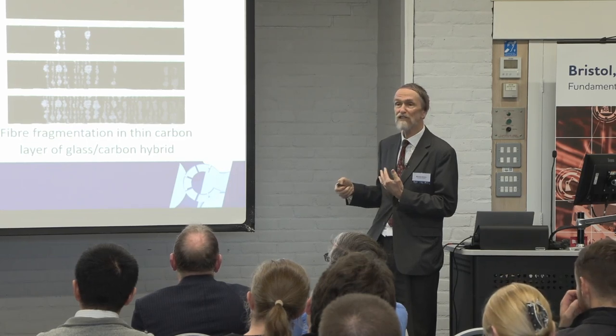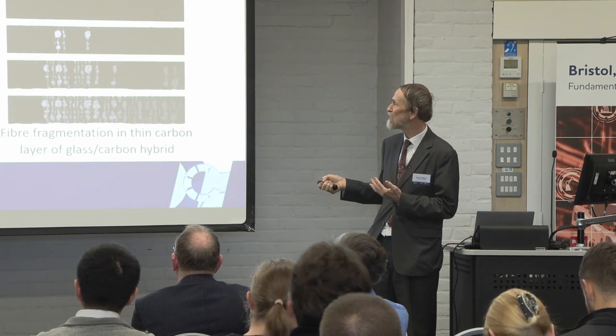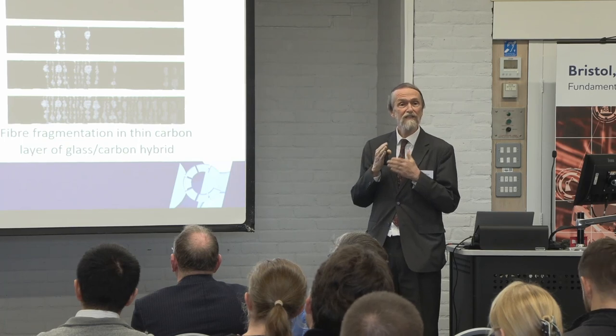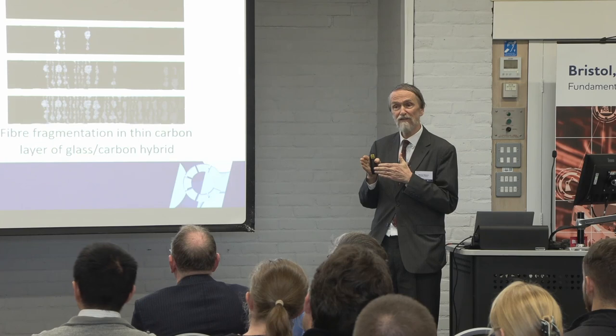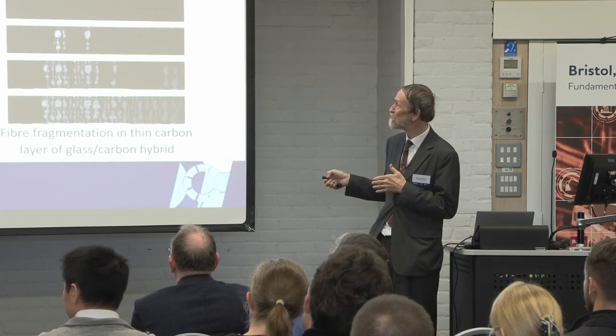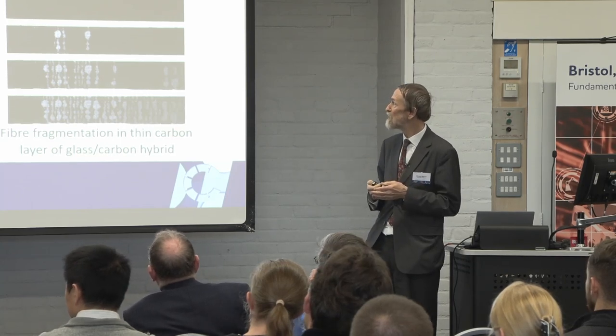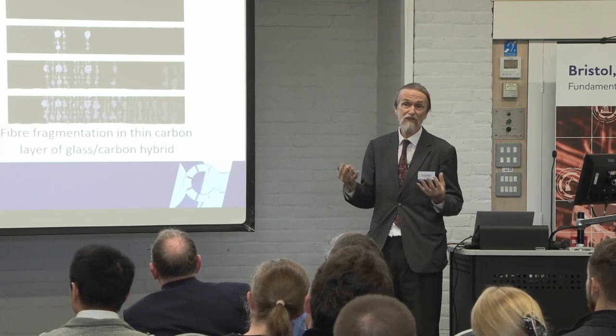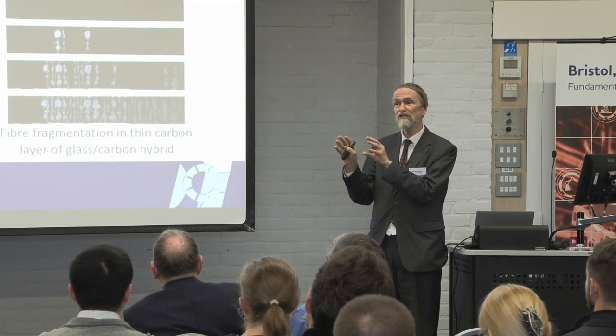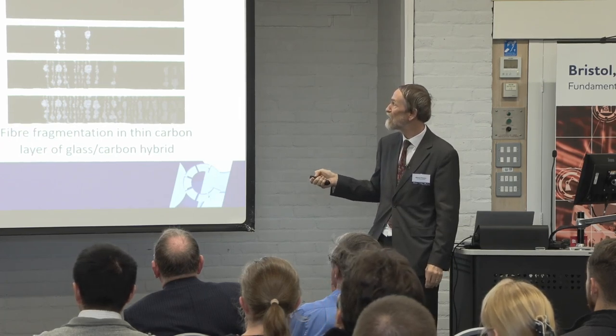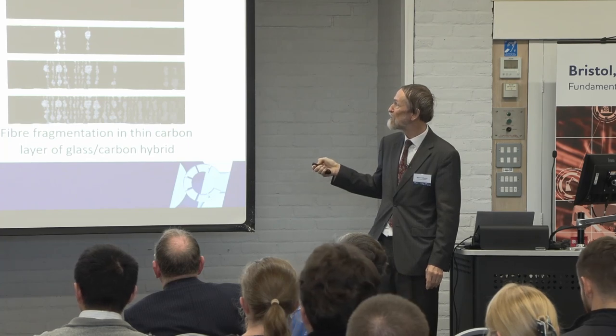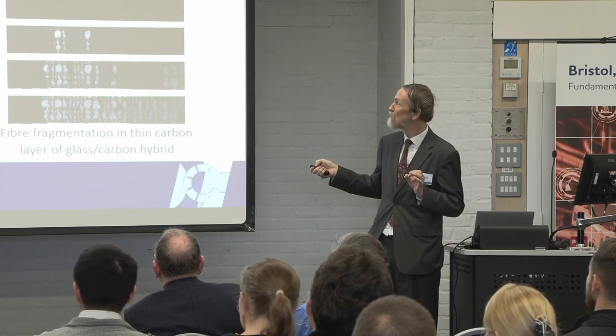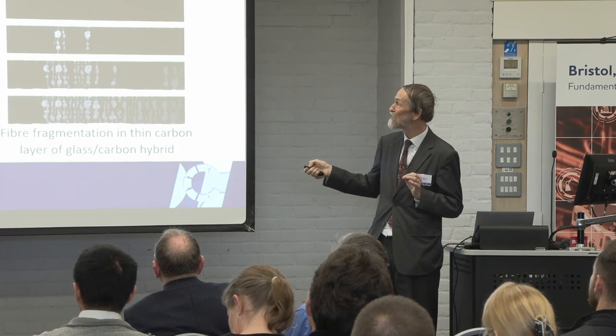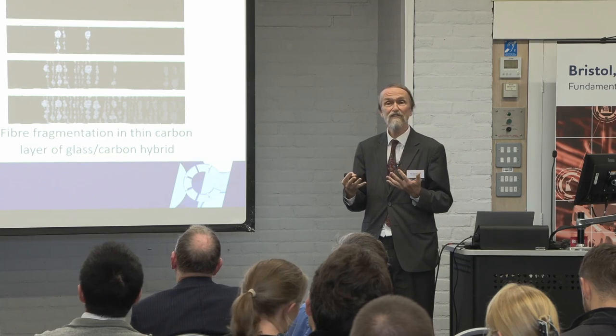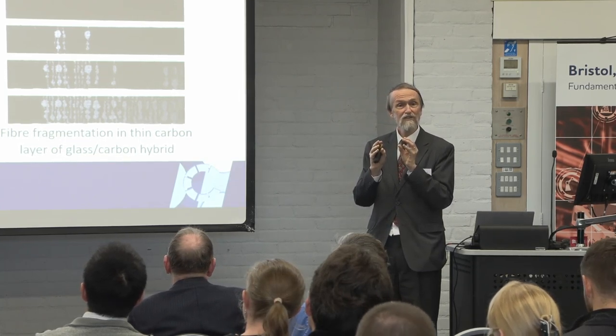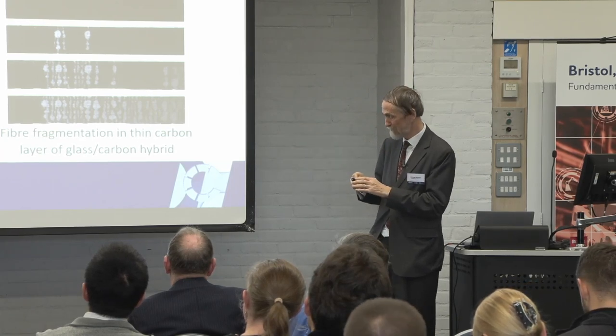And we also showed that this could also be done with different orientations. So here we've got, rather than hybridizing different carbon and glass, we've used different orientations of the material, an angle ply carbon with a unidirectional carbon, and in the same way been able to get this pseudo-ductile response. And as well as showing this plateau on the stress-strain plot, it also gives us notch insensitivity, which is one of the key reasons for doing it, of course. In a metal, you get local plasticity around a stress concentration, which relieves the stress. And we see the same thing happening. And here, we see this curve here is the baseline material. But then when we do a specimen with an open hole, effectively we get the same net section stress as this pseudo-yield stress we get in the unidirectional material. So we've got rid of that notch sensitivity because the damage occurs around the hole, the stress concentration relieves the stresses and allows us to go further before ultimate failure. So that was tension.